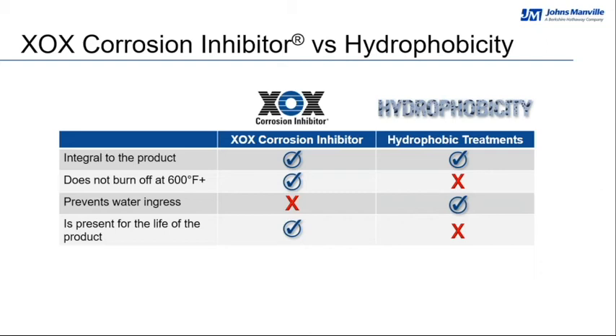Sorry about that, folks. Take a quick look, a little bit of a summary of the two different properties we've just been reviewing with you with regard to features that can be incorporated in insulation materials to protect against corrosion under insulation. You can see in the right-hand column, insulation materials that have hydrophobic or water repellent properties. Typically, this is something that is integral to the product, though in some cases it can also just be a topical or surface treatment. These treatments typically do oxidize off at temperatures between 300 and 600 degrees, as we discussed earlier. They are designed specifically just to prevent the ingress of water into and through the insulation system, and depending on the process operating temperatures, will not be present for the life of the insulation system. They will oxidize off and therefore not be there.